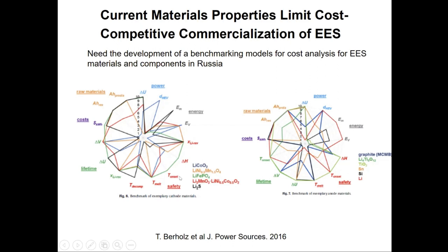So here down below is listed some of the more commercialized materials that you might have heard about, lithium cobalt oxide being the first one commercialized in 1990 with the discovery by John Goodenough, Nobel Prize winner of 2019. And then there's the nickel manganese spinel, the olivine lithium iron phosphates, and also more complex so-called excess lithium materials or NMC, so cobalt, manganese, nickel oxides and lithium sulfur. And you can see that in terms of some of the performances for either cathode materials, and then there's also listed here for what you choose as the cathode or the anode, excuse me, that there's trade-offs. Not one material solves all of the particular problems.